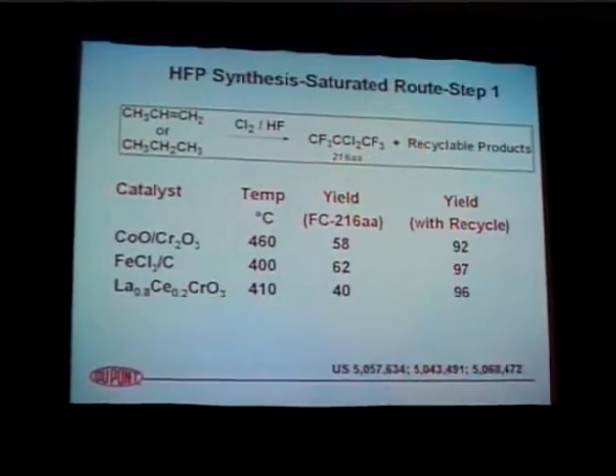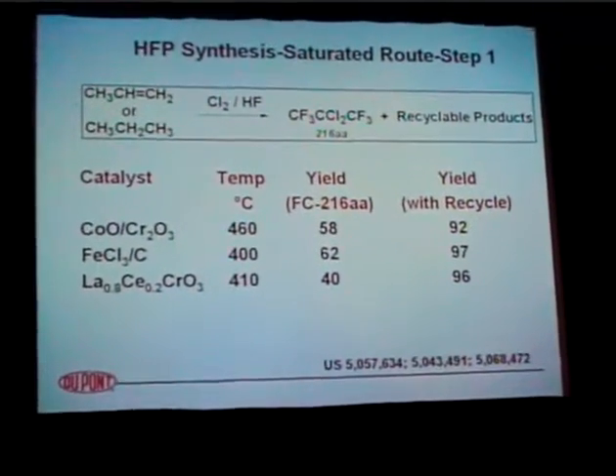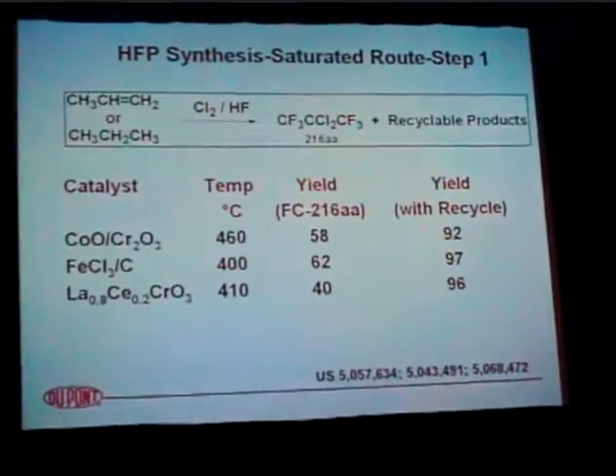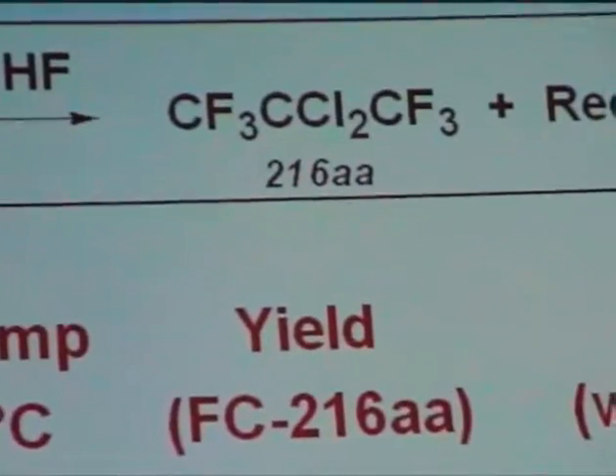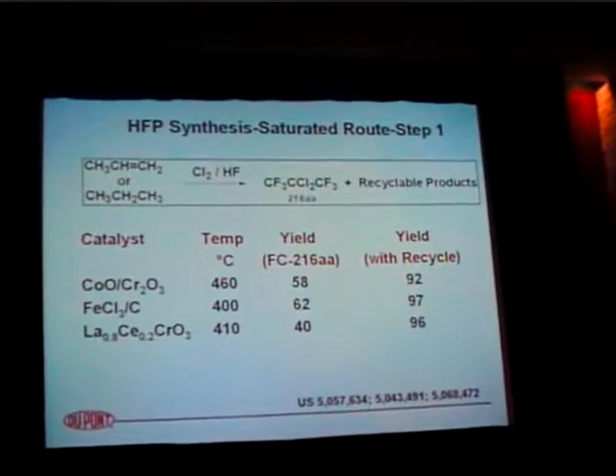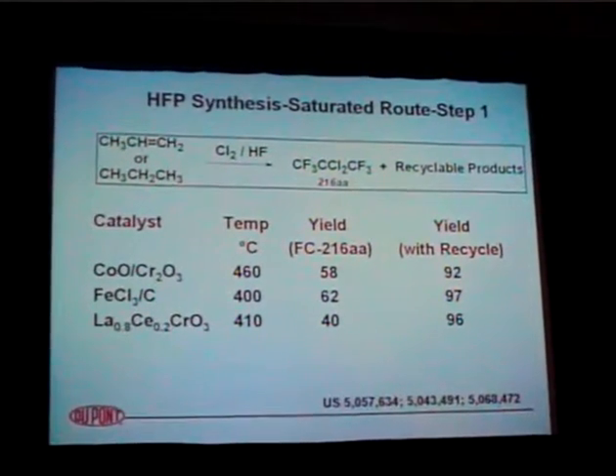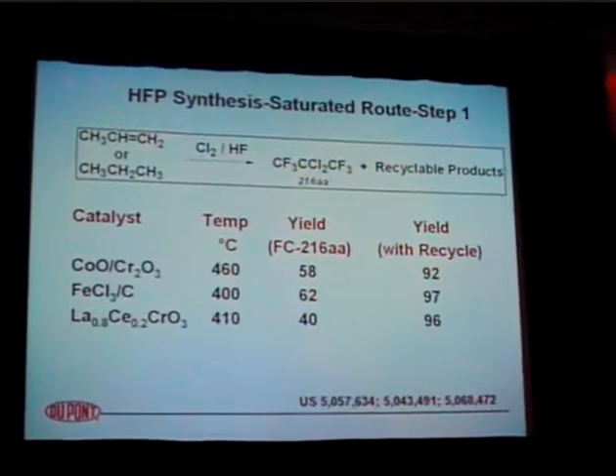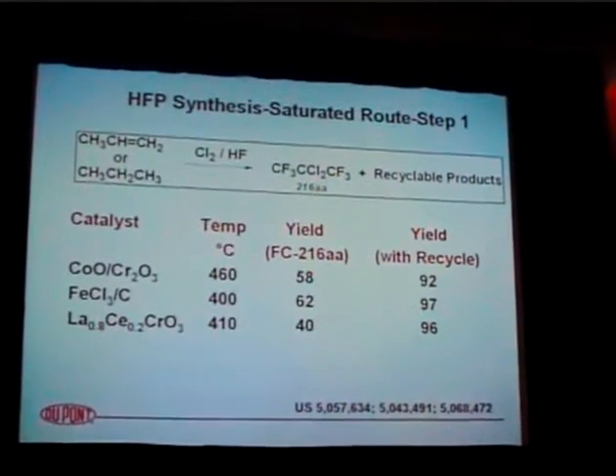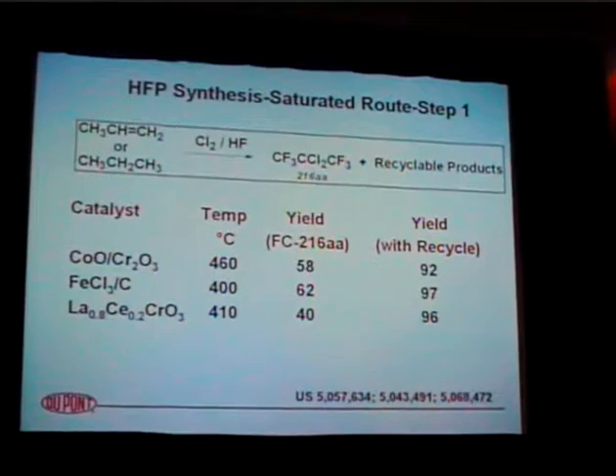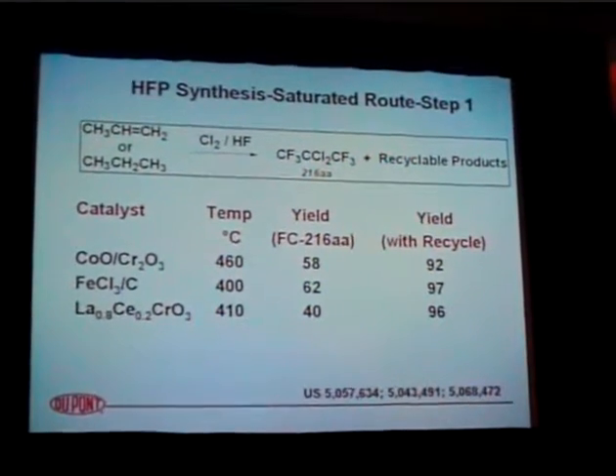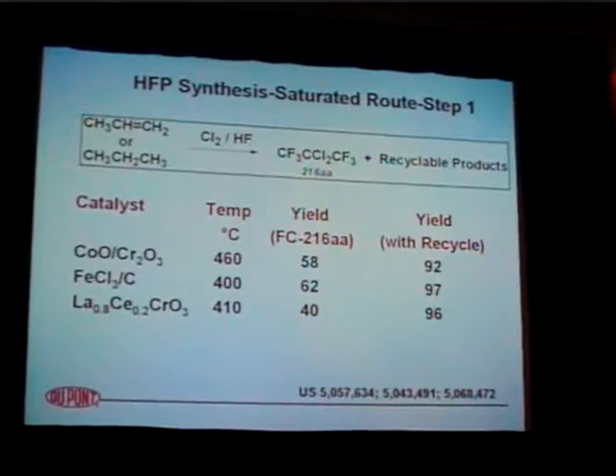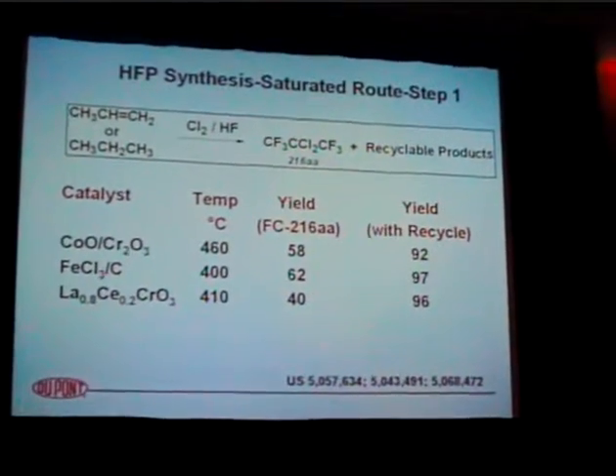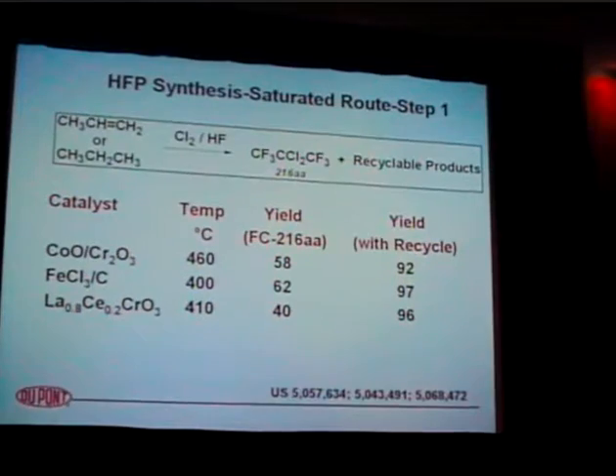Starting with propylene or propane, it really doesn't matter, with chlorine and HF over the catalyst shown there, you can make 216aa, dichlorohexafluoropropane, in about 50 to 60% single pass yield. An excellent catalyst. That only takes place if you promote the chrome with a little bit of cobalt. Iron chloride is a pretty good catalyst, and a perovskite, lanthanum cerium chrome oxide, works reasonably well for that reaction. So the overall yield is about 97% directly to that 216AA, that's about half of the product mix.